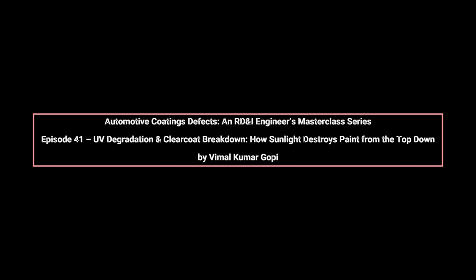Environmental factors amplify UV damage. High ambient temperatures accelerate oxidation kinetics. Acid rain and atmospheric pollutants catalyze surface reactions. Repeated wet-dry cycling washes away degraded polymer fragments, exposing fresh material to further attack and leading to progressive thinning of the clear coat. Clear coat breakdown becomes visible when the degraded surface layer loses cohesion.